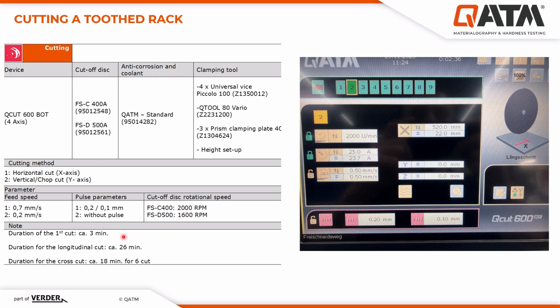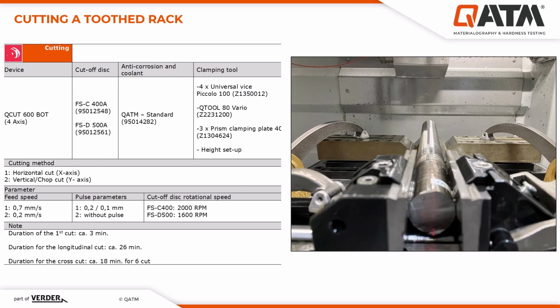The duration of the first cut that puts the part into two is 3 minutes. The duration of the longitudinal cut is 26 minutes, and the cross cut for 6 cuts is 18 minutes. It means that each chop cut is 3 minutes, and the longitudinal cut is 26 minutes. As you can see here, we clamp the sample on the end with QTOOL 80 Vario, and we put 2 prisms to support the sample. And as you can see here, the longitudinal cut is a completely direct cut without any deformation on the sample.